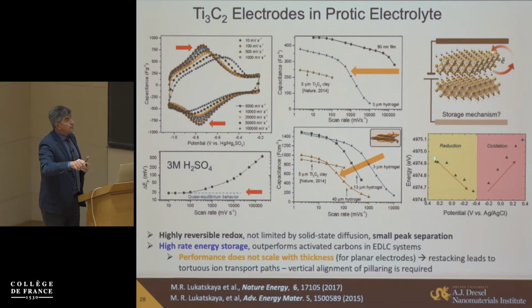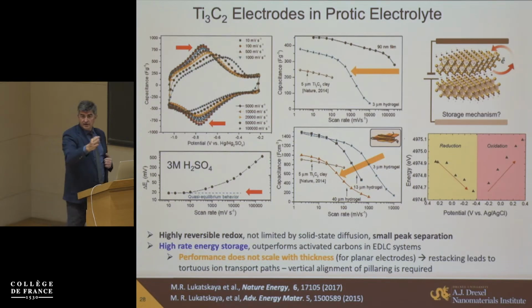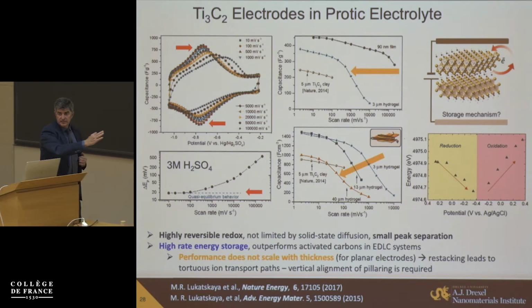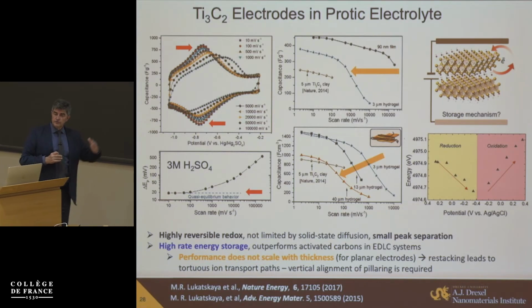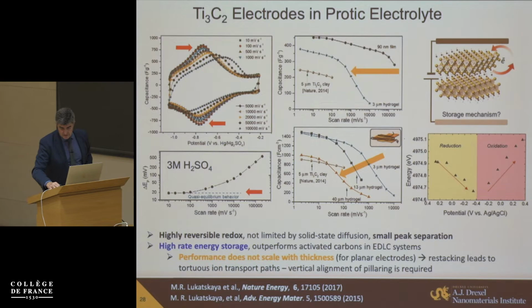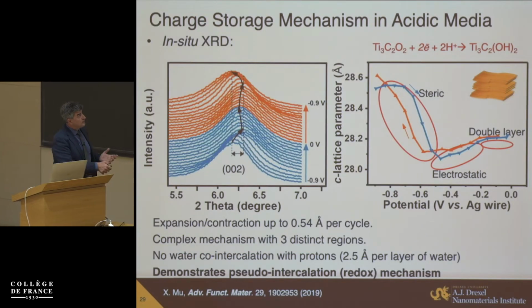And we also know from in situ X-ray absorption spectroscopy that this process is a reversible redox in titanium. So the X-ray absorption spectrum of titanium shifts up and down. So we go from oxygen to OH, basically, on the surface of these materials. And we also can monitor.